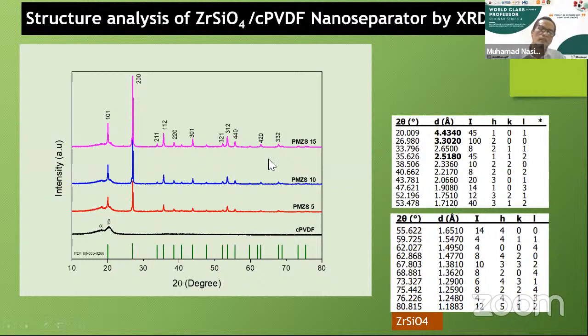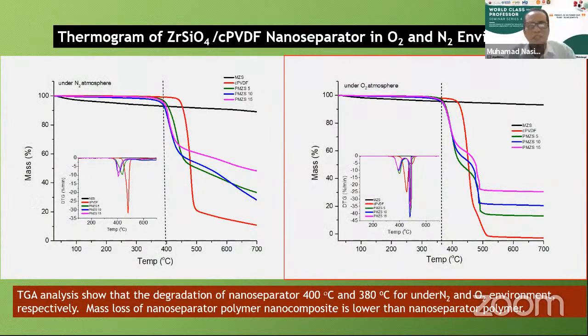And then we confirm again by using the XRD. We can see it's very clear. You can see here the crystal phase of the co-PVDF, alpha and beta, and this is the 2 theta peak of the zirconia silicate. It's very clear. And then we study the important point of why we use the zirconia silicate. You can see here we do the experiment in nitrogen and under oxygen atmosphere. We can see here when we use zirconia silicate, the degradation rate of the decomposition will decrease. So it's very important if we use lithium ion battery in the high temperature.